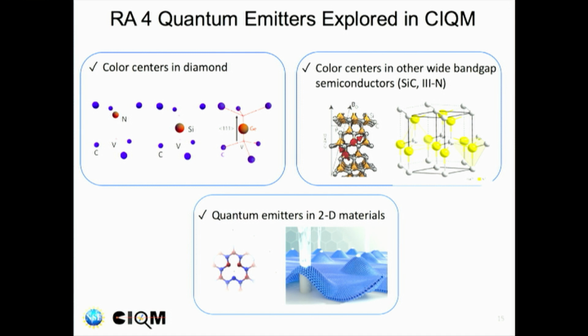But there's a disadvantage in that it couples to phonons, which you don't want because that makes it incoherent. The solution is to put silicon in instead. It turns out the silicon has two vacancies, one at the top, and strain-wise, instead of being a dipole, it's a quadrupole. And so it doesn't couple to the phonons very well, so that's a great advantage. There's a lot of work now on silicon vacancy centers, because the optical response is much more pure. And people are looking at other things, for example germanium in the same situation, as well as other materials.